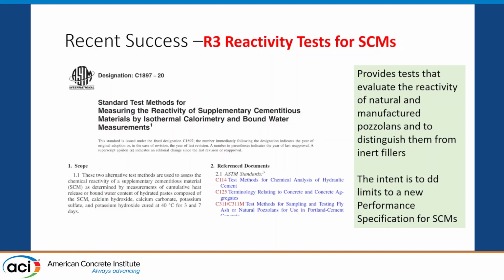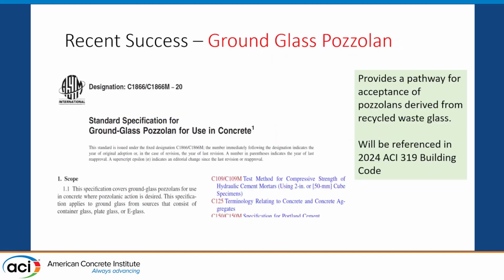So we developed a reactivity test as part of a RILEM committee I was involved with, and I championed this through the ASTM system to get this reactivity test, the so-called R3 test, using isothermal calorimetry as one method and just bound water measurements as another, to evaluate whether pozzolans are actually reacting, and we have a standard for it, which we're hoping to incorporate in a performance spec for SCMs.